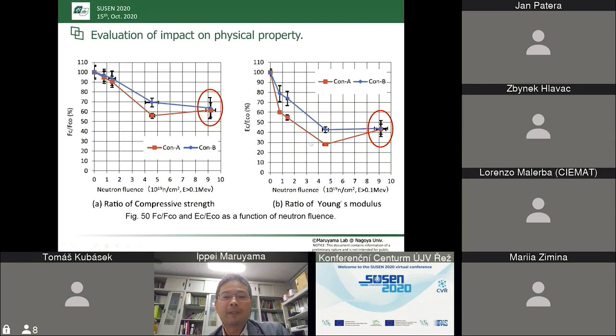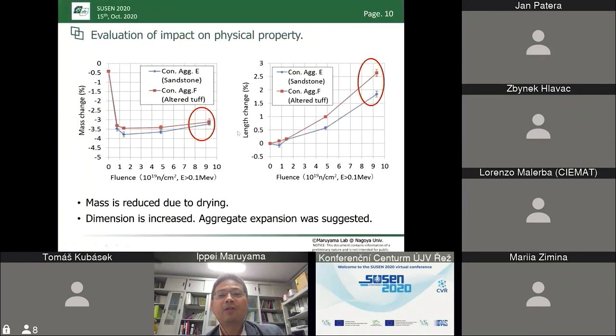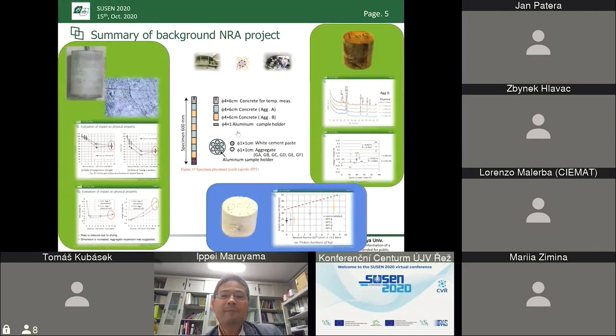And we prepared two different concretes, which contain two different kinds of coarse aggregate. One has a high amount of quartz, and the other is a general sandstone. When we use a large amount of quartz in the coarse aggregate, it expanded much, and it showed a large reduction of the compressive strength. The other sandstone aggregate shows a relatively mild reduction, but still we see the reduction of the concrete strength and the Young's modulus. So we have to identify the mechanism of this degradation. And we did the irradiation experiment on aggregate samples and did some PIEs.